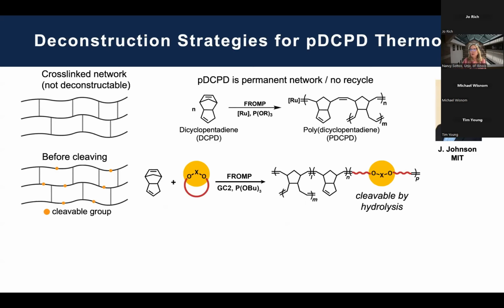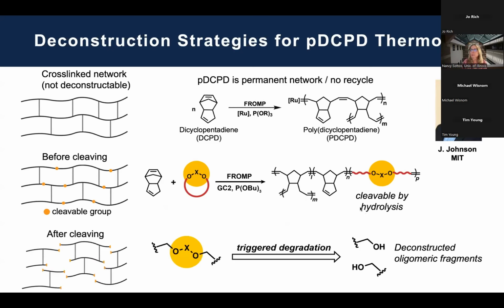And we've been teaming with Jeremiah Johnson's group at MIT. Jeremiah Johnson is in the chemistry department there and has been working on these cleavable strategies. Actually, this is a great COVID collaboration that started over Zoom. But the idea is to introduce these cleavable groups into the backbone of the monomers. And the idea is, can we also energy efficiently frontally polymerize these systems? And then basically we have these groups that are cleavable by hydrolysis that will let us recover oligomeric fragments.